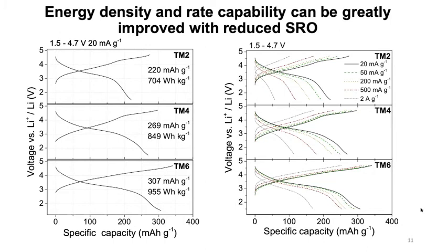And remarkably for TM6, even when you cycle at 2 ampere per gram, it still shows a discharge capacity around 170 milliamp hours per gram. And this proves that DRX material is not only a slow material, but it can achieve high rate capability if we somehow optimize the short-range order.